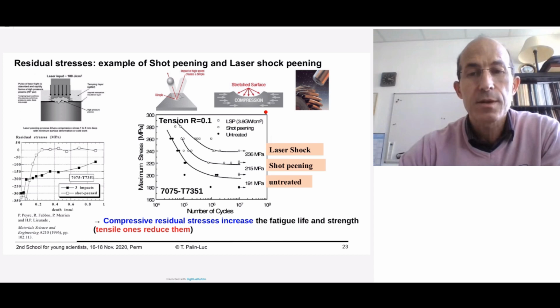You can see an illustration in this SN curve in tension with a positive mean stress on an aluminum alloy, and you can see that the reference material has the fatigue resistance around 190 megapascal, it is increased by shot peening or laser shot peening by a significant factor. So this is very important in fatigue for designing components to consider the residual stresses. They are favorable to the fatigue resistance in compression, and they are deleterious if they are in tension.